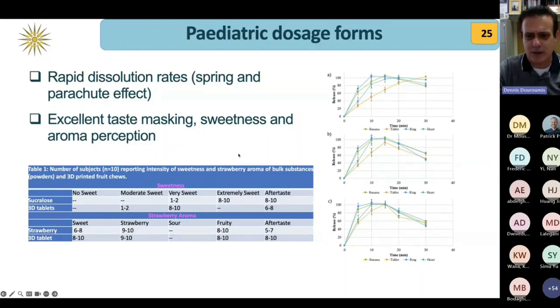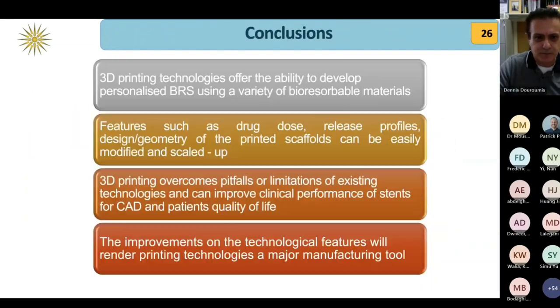And on the side, you can see some dissolution profiles that actually, for those who are not familiar, show that the release is almost immediate. Within 10 minutes, we have a release of the API, which means we can have a very fast onset of action when this is administered to children or any patient. So these are some of the benefits.